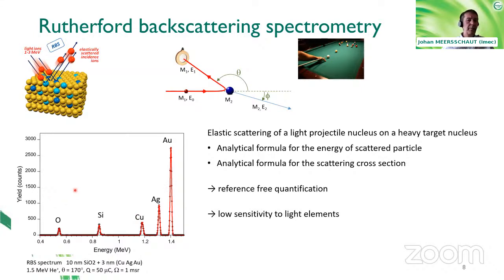In this experiment, we have 1.5 mega electron volt helium particles impinging on a stack of thin films of copper, silver, and gold deposited on 10 nanometer of silicon oxide. You can see that the energy of the backscattered particles on a gold atom, on the gold nuclei, is much higher than the energy of the backscattered particle on lighter elements, like, for example, silver, copper, silicon, or oxygen. And these things can be perfectly calculated in a classical way. So this leads, if you count the incoming helium particles, to a reference-free quantification of the number of atoms that are in the sample for a specific species.